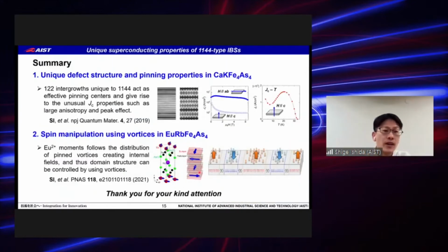To summarize, for the first part, we observed 122 intergrowths unique to 1144 materials, which act as effective pinning centers and give rise to unusual Jc properties, such as the extremely large Jc with field around the AB plane and the anomalous peak effect in the temperature dependence of Jc.